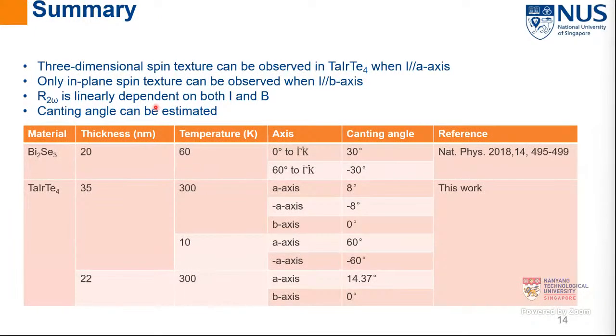In summary, the three-dimensional spin texture has been observed in TaIrTe4 when current is flowing along the A-axis, while no Z spin can be observed when current is flowing along the B-axis. And the second harmonic resistance is linearly dependent on both current and field. The canting angle can be estimated from this measurement. The published data is for a 20 nanometer Bi2Se3 film at 60 Kelvin, where the canting angle is 30 or minus 30 degrees depending on the current direction. In our experiment, for a 35 nanometer device at room temperature, the A-axis is 8 degrees and the minus A-axis is minus 8 degrees, while along the B-axis it is 0 degrees. A 22 nanometer device shows a canting angle along the A-axis, but no Z spin along the B-axis.